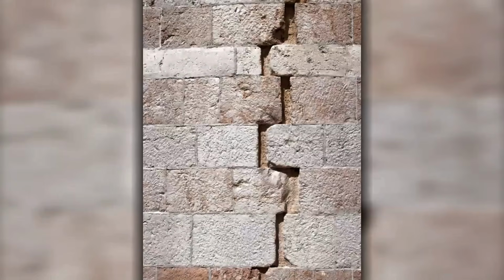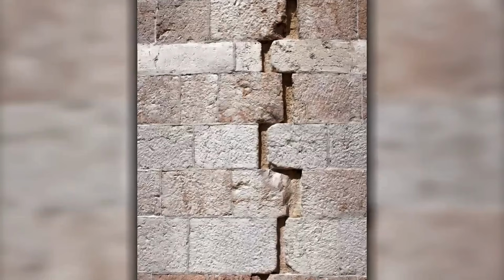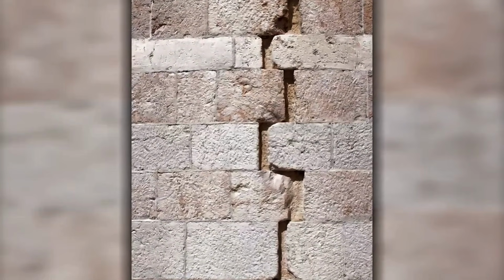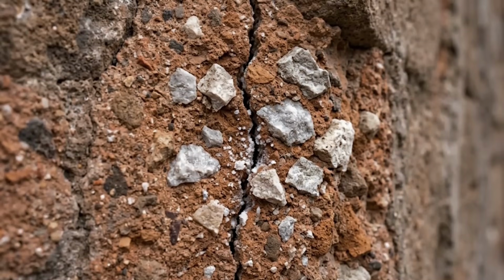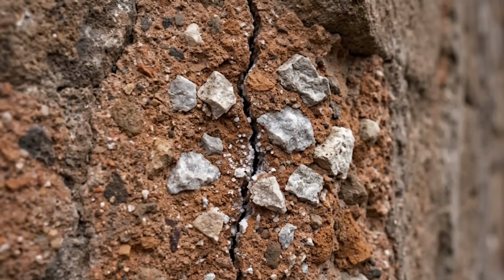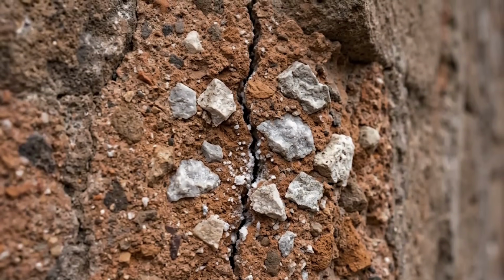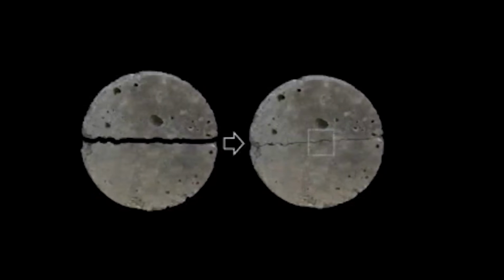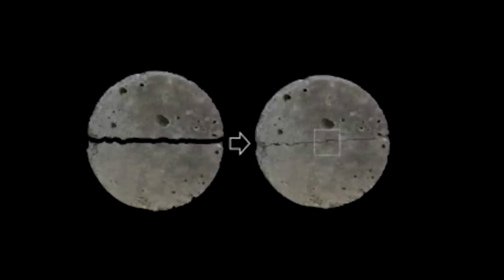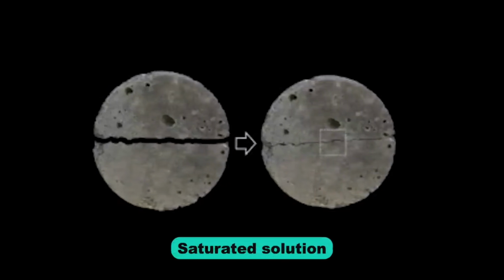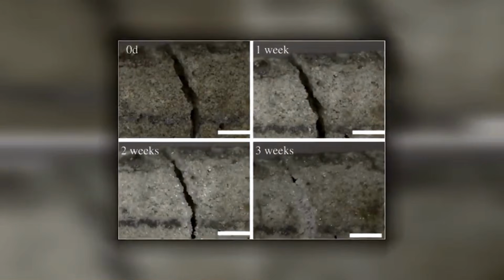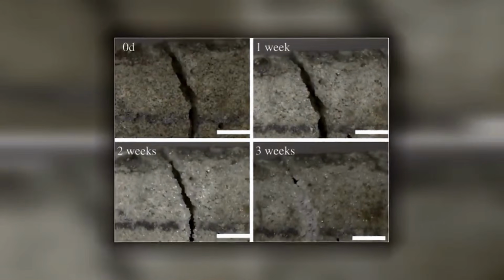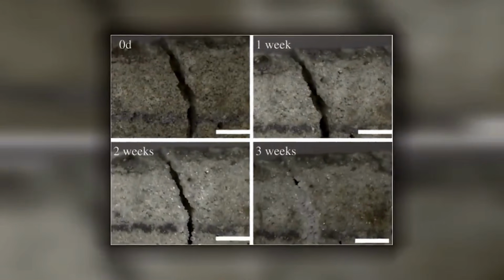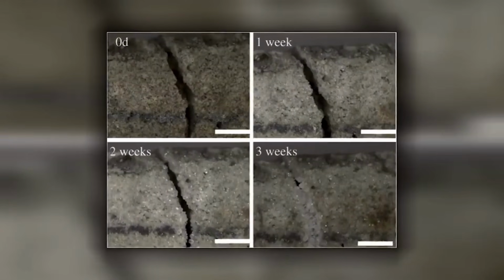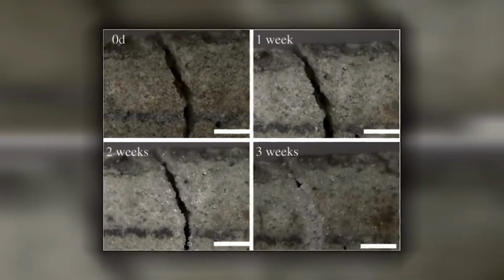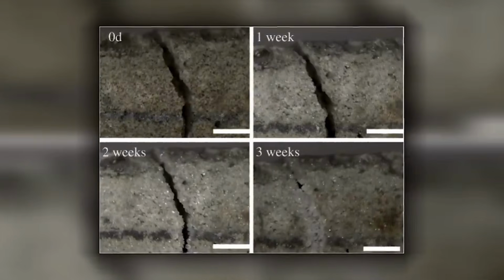The mechanism is almost embarrassingly simple. Picture a hairline crack opening in a Roman wall. The lime clasts embedded in the mix are reservoirs of unreacted calcium carbonate. When water reaches a clast, it dissolves it. The dissolved calcium flows into the crack as a saturated solution, and when it loses the water by evaporation, it recrystallizes as fresh calcium carbonate, the same mineral. The crack fills itself in real time, and the wall keeps standing.